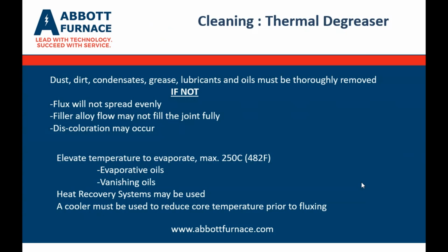So the main thing is to get an MSDS sheet of what you're using, find out what that flash point temperature is, and then that would become the target of the thermal degreaser. Generally, about 500 degrees Fahrenheit or 250 degrees C is a general operating temperature of your thermal degreasers.